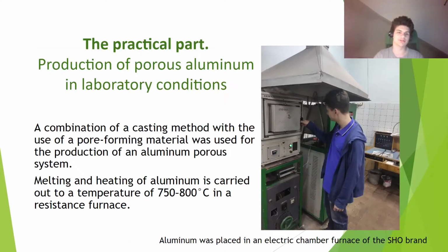The practical part. A combination of casting methods with the use of pore-forming materials was used for the production of an aluminium porous system. Melting and heating of aluminium is carried out to a temperature of 750 to 800 degrees Celsius in a resistance furnace.